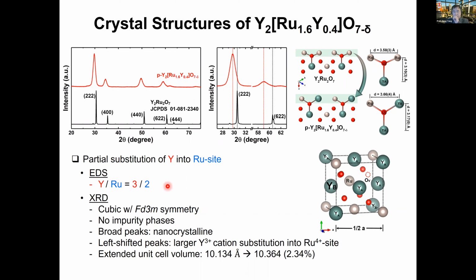We are currently still trying to understand the thermodynamic origin of this type of structure. Our early assumption is that by having the yttrium substitution of B-sites, we could create oxygen vacancies, and that depends on the size of these two. If you compare the far right on the top, this is the ruthenium, and this is the partially substituted yttrium case. You can see that the bond length changes, and this could lead to a different type of stability. This is a study we are currently still doing.